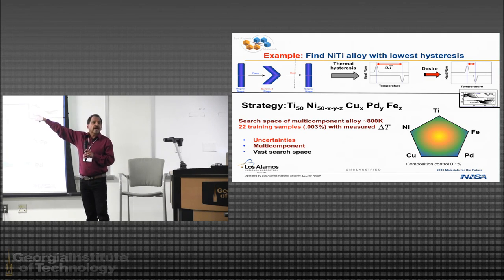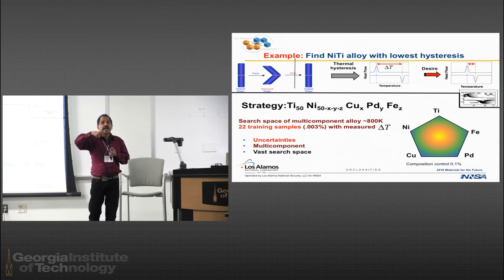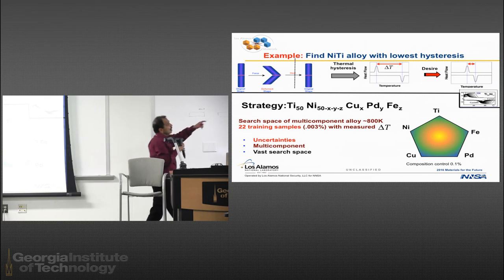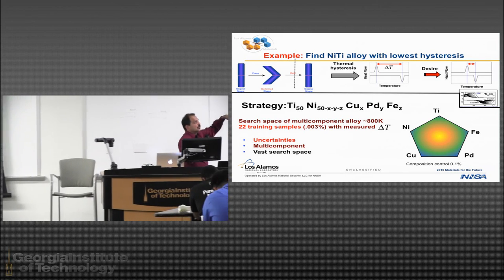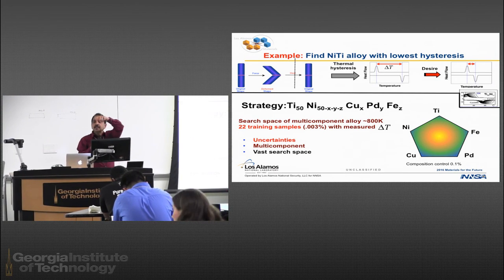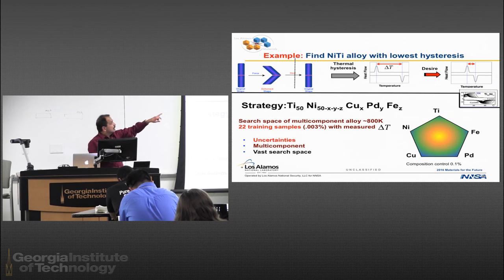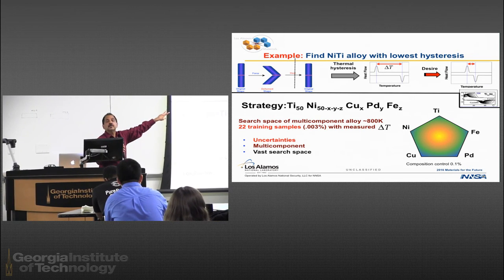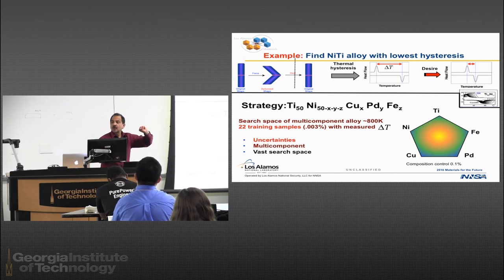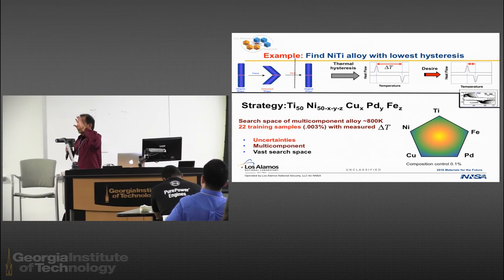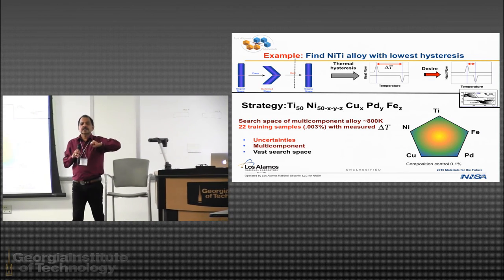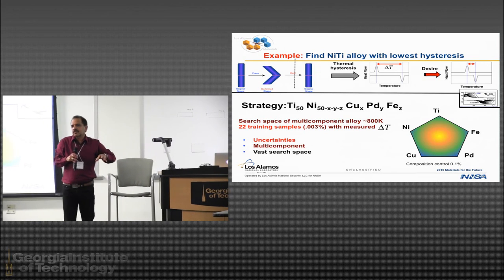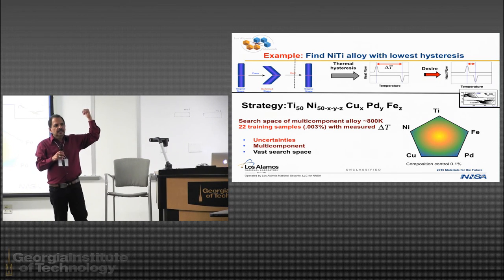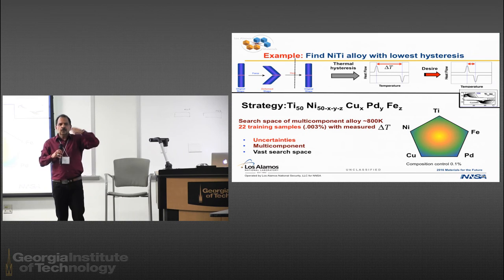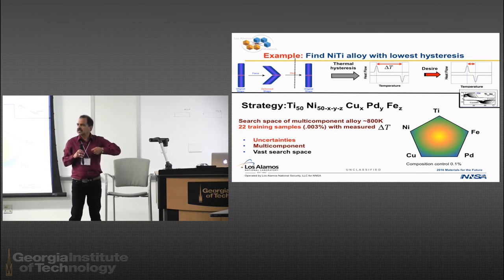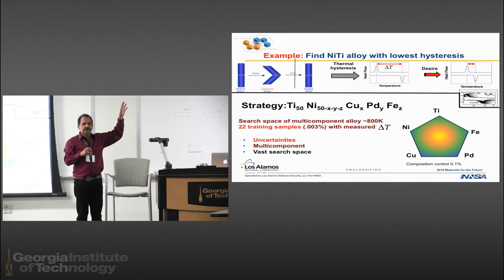The way you monitor that is through differential scanning calorimetry. And so you basically look at the heat flow. So you heat, you get a peak, and you cool, you get a peak. The hysteresis is the interval between those two, right? So for a material, what you want is to minimize that hysteresis. Why do you want to minimize that hysteresis? Because that's what affects fatigue. And you want something that can go through many, many cycles without fatigue. That's your target. That's what you want.